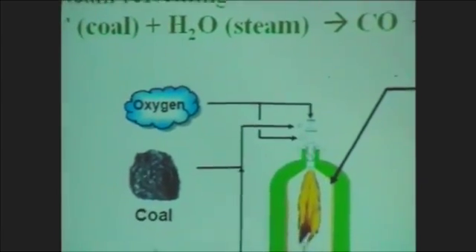And if we can find a catalyst to catalyze these reactions, then we probably can decrease the temperature, and then the gasification probably can run in a much more effective manner. And in fact, there's a lot of research on catalytic gasification in the 1970s and 1980s. And most of that research stopped simply because of catalyst deactivation and also the difficulty of separating the fly ash from the catalyst. So research on this reforming reaction, steam reforming, steam gas, coal gasification reactions, has almost completely stopped.